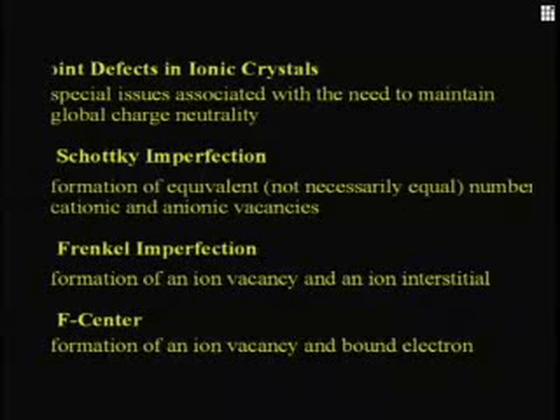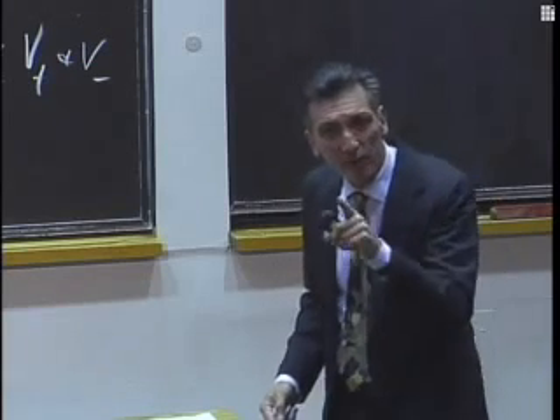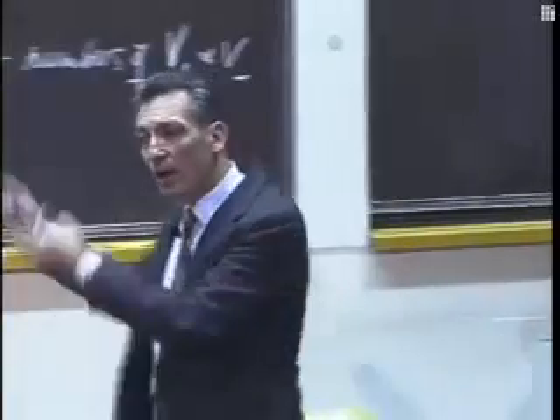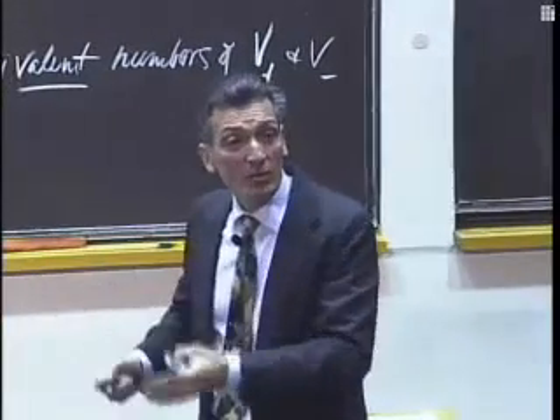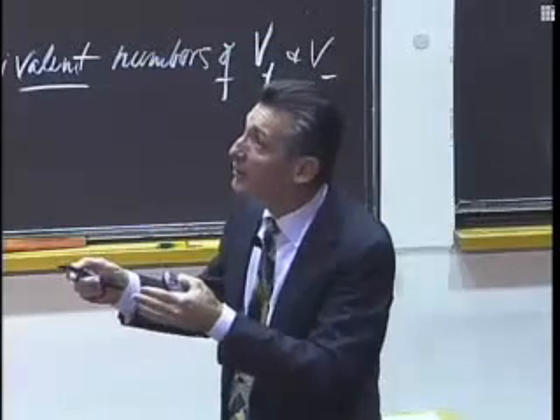Okay, so there's another way, though. There's another way to make vacancies, and that's called the Frenkel imperfection, and it's the formation of an ion vacancy and ion interstitial. So that's shown over here, where the little cation, you see the cation? This cation's gone over to another place in here. There's an interstitial in here. You see the little cation? Cation left and went over here. But see, it didn't leave the crystal. It moved to another place in the crystal, so I don't have to worry about compensating with the ion of opposite charge, because the total cation population hasn't changed.